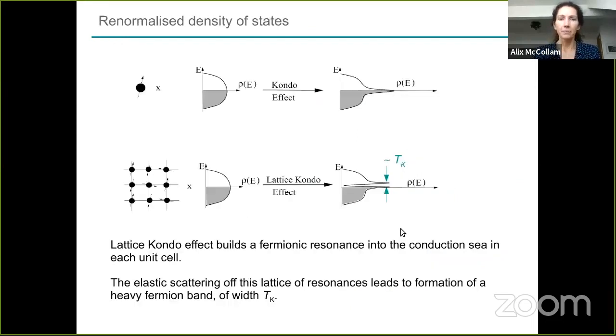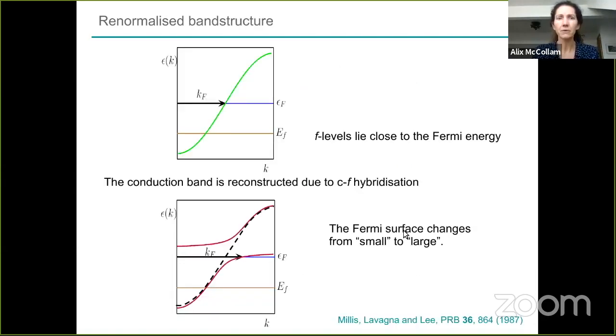Okay, so in this picture, when you have local moments on a lattice and they're interacting with the conduction electrons in this way, our lattice Kondo effect gives us a renormalized density of states. In the single impurity case, you get a resonance here, but in the lattice case, you actually get a band forming that has some finite width, which is approximately proportional to the Kondo temperature. You get a renormalized density of states, and this also gives you a renormalized band structure.